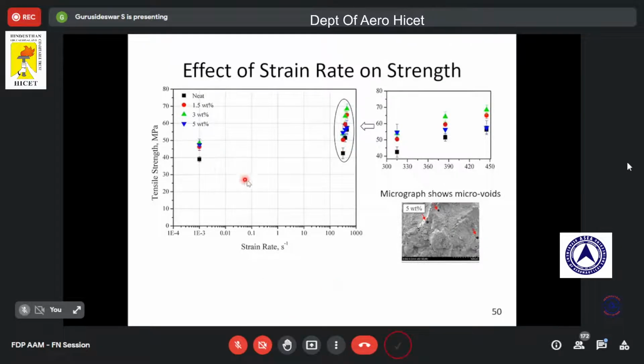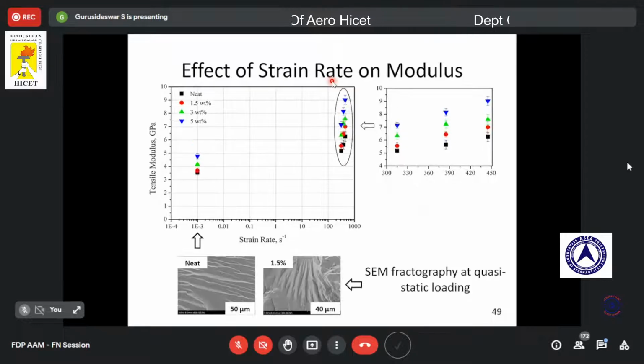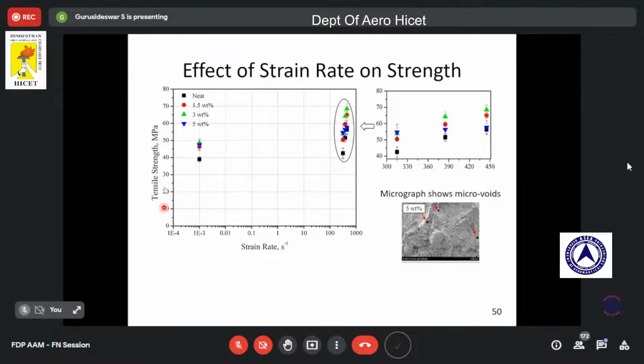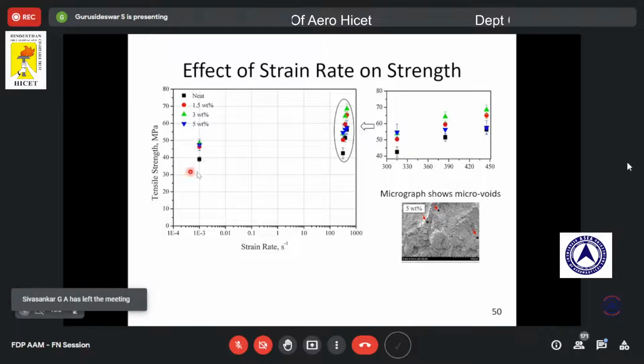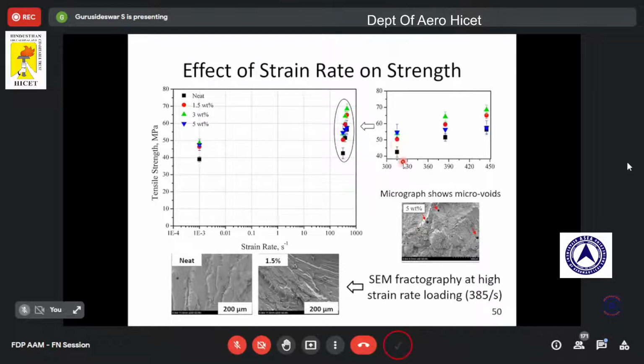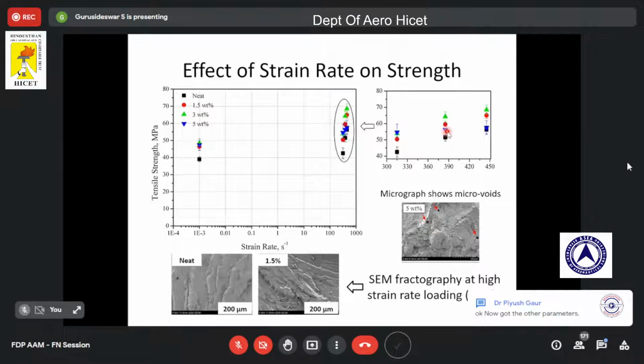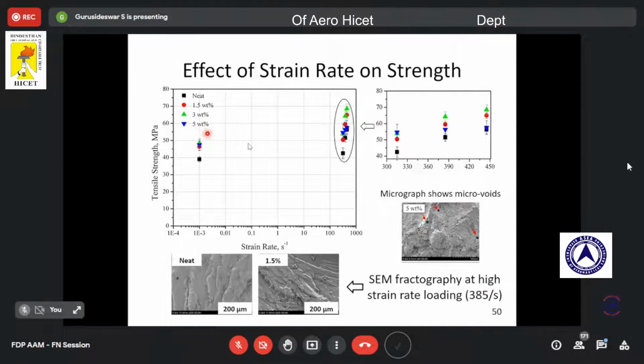And again, this figure shows the effect of strain rate on strength. In the previous slide, I was focusing on modulus, where the y-axis was tensile modulus. Now I wanted to focus on strength. So here you can see the variation of strength at different strain rates and at different clay loading. One can observe that the strength at higher clay loading is not good. The blue shows the 5% clay loading, but we may end up with micro voids. These micro voids lead to premature failure. So that is why the improvement of strength for higher clay loading is limited.